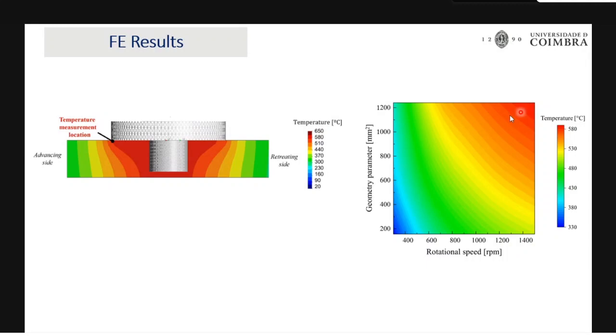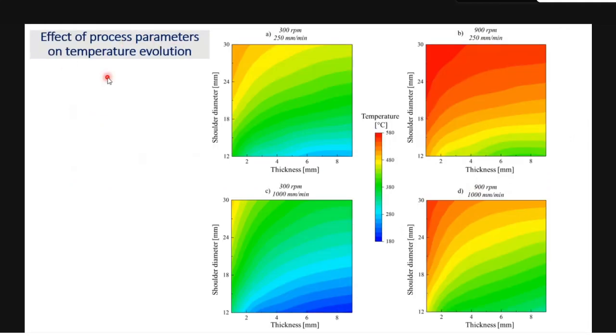This can be related to the fact that when the tool dimensions increase, you will have more contact area and more friction, so you will have higher temperature. Coming to the process parameter and temperature evolution, here the shoulder diameter and thickness are compared. As the plate thickness increases, you are not getting higher temperatures; only the lower thickness has higher temperatures. The reason is that the heat will be lost from the contact region or the stir region because it is a thicker material, so the heat loss will be higher due to heat conduction.